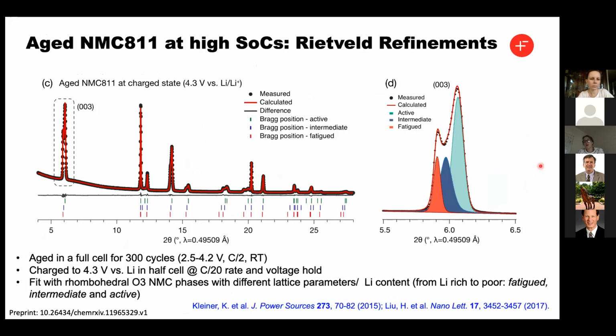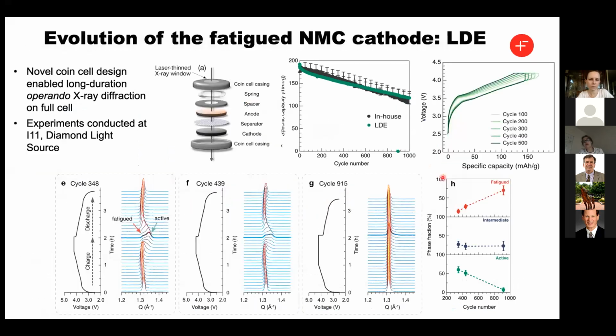And you can then model what's going on, and you can see that you no longer see a single phase, but you see phases or components that no longer fully cycle, which we call the fatigue phase. And we can then analyze this over multiple cycles. And as the cycle number goes up, the fatigue fraction goes up. And so by the time you cycle it for about 915 times, pretty much all of the phase is fatigued and isn't able to cycle over the full range.